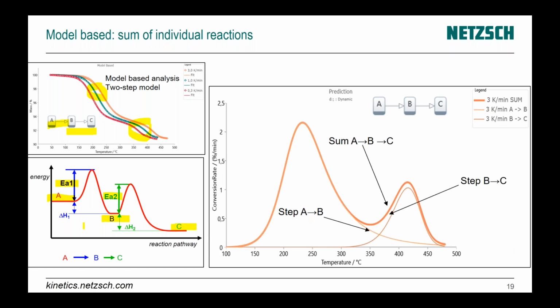Finally, we can just select this model in the software, and the software shows that the first reaction, here is reaction rate, conversion rate. The first reaction has one step here, and it goes slow to zero. A second peak is something like this here. The final signal is a sum of these two peaks, and somewhere here we have two parallel reactions which go in parallel.